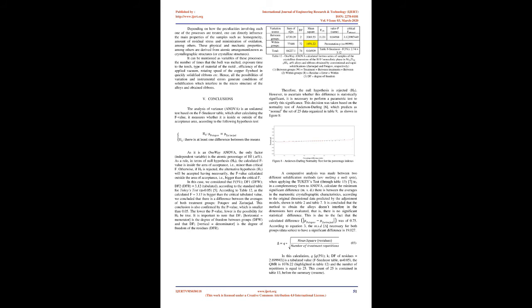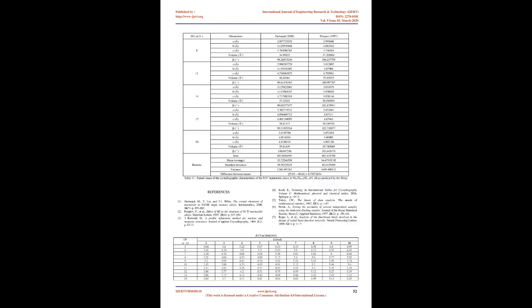are also sensitive to the peculiarities of the 2 production processes as well as the typical variables of each one of them, electric arc melting, and quick solidification melt spinning. Figure 7. Figure 7, plot of the probability curve, 100 points, of the difference indexes estimated by the statistical models adopted for Zarinejad alloys, 2008, and Potapov ribbons, 1997. Depending on how the peculiarities involving each one of the processes are treated, one can directly influence the main properties of the samples such as homogeneity, amount of residual stress and minimization of oxidation, among others.